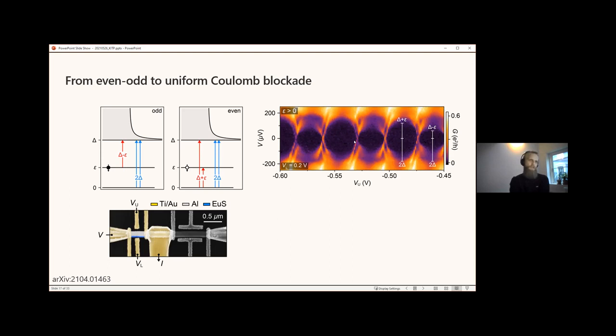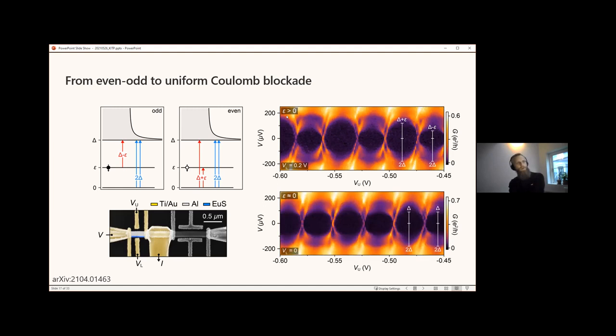In addition to that, we can also change the gate voltage. If we change, in this particular case, from 200 millivolts to zero, the Coulomb blockade evolves from even-odd to uniform periodicity. Basically, the consecutive Coulomb diamonds become nearly identical, indicating that the energy of the subgap state decreased to zero, because the first Coulomb feature happens at the same energy in both Coulomb diamonds.